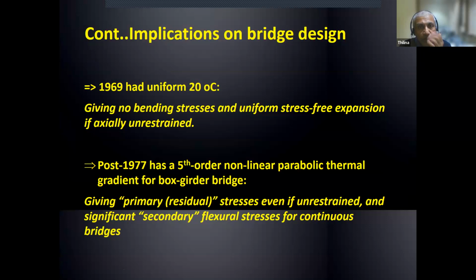From those two diagrams, 1969 is a uniform 20 degrees. So if it is a bridge deck, it expands uniformly. If it is on bearings, it's stress-free, no stresses at all, because it is axially unrestrained. But post 1977 there is a fifth order nonlinear parabolic thermal gradient. Even if it is unrestrained, we get primary or residual stresses. And if it is restrained, we get secondary flexural stresses.